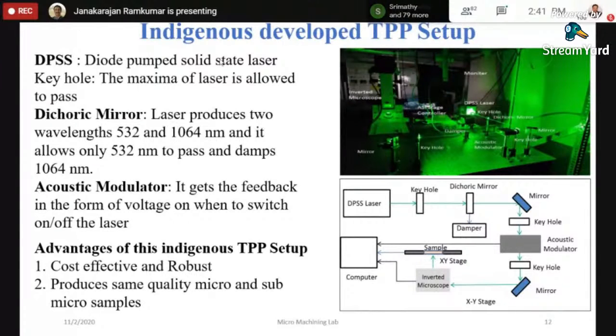If you see there, from the diode pump laser you have a keyhole, and then you will have 1064 and 532. 1064 is damped, and 532 is passed further into a mirror. From that mirror, it passes through a keyhole, then through an acoustic modulator. From the acoustic modulator, it passes through a keyhole, then a mirror, then we used an inverted microscope. From the microscope, it projects onto the XY stage, and we could develop a single layer of information. But the Z height was constant. When you start building several of these layers one above the other, it forms a 3-dimensional object.